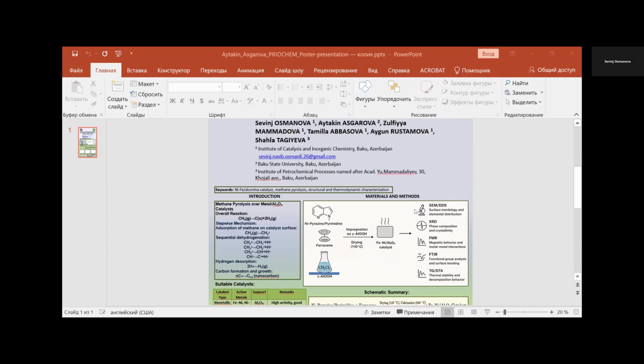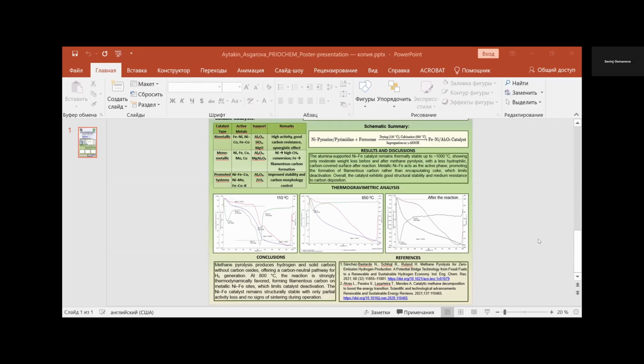Among different systems, nickel-iron catalysts supported on alumina have shown excellent activity, stability, and resistance to sintering. In our research, we prepared nickel-iron alumina catalyst by impregnating nickel pyrazine and pyrimidine complexes onto alumina. The catalyst was characterized by different methods, including XRD, SEM-EDS, FTIR, and thermal analysis. Our findings show that the catalyst remains structurally stable up to 1000 degrees Celsius. It promotes filamentous carbon formation, which helps prevent deactivation. In conclusion, the nickel-iron alumina catalyst demonstrates high thermal stability and efficiency, providing a sustainable and carbon-neutral pathway for hydrogen generation through methane pyrolysis. Thank you for your attention.